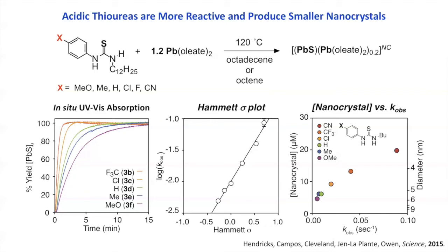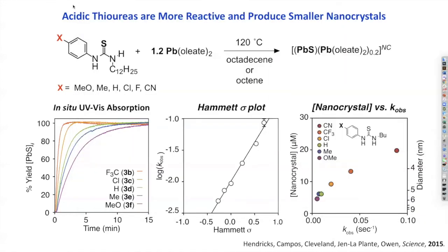So at 400 nanometers, the absorption spectrum is not strongly size dependent. The extinction coefficient is not strongly size dependent. It's just proportional to the volume of material. So this is an energy where the E versus K diagram is not discrete, but kind of continuous, and it just looks like a bulk semiconductor. So you can monitor the amount of lead sulfide being formed by measuring the absorption of the solution at high energies. And you can see smooth curves here.